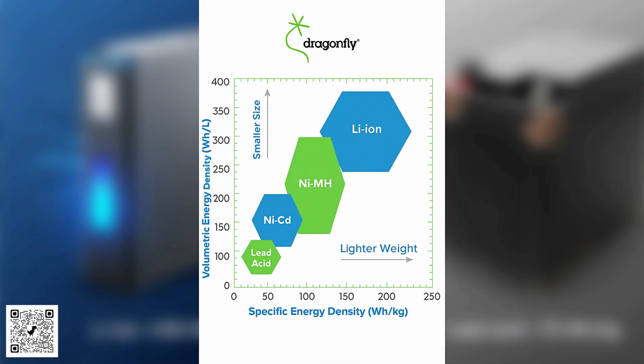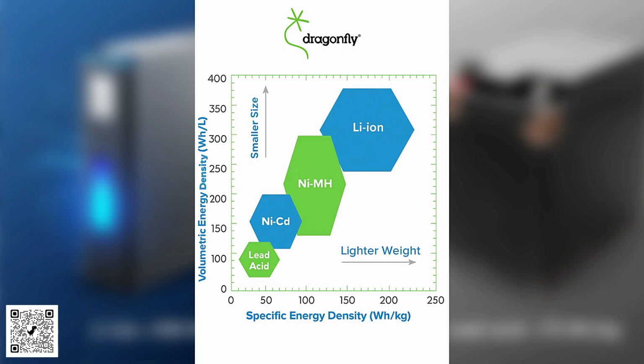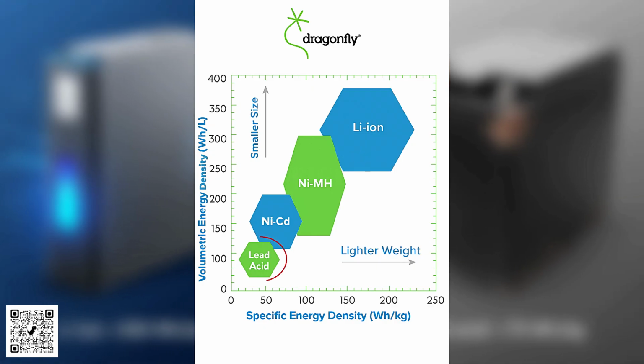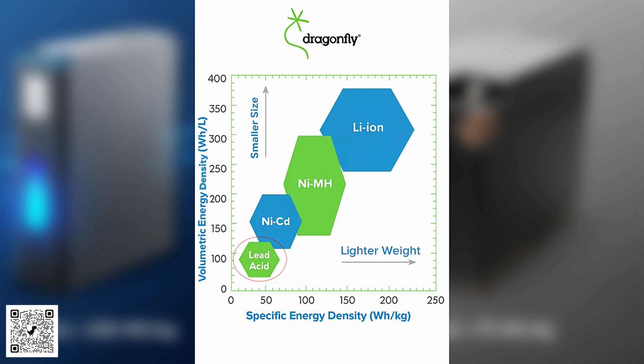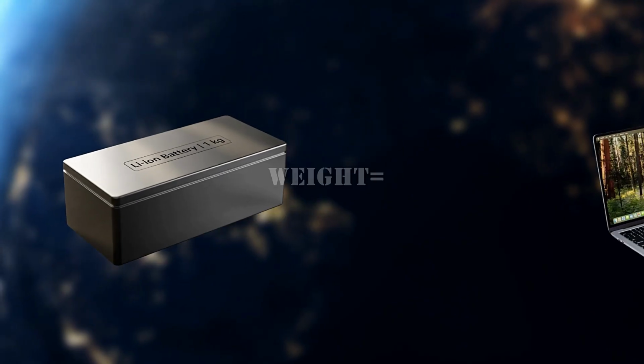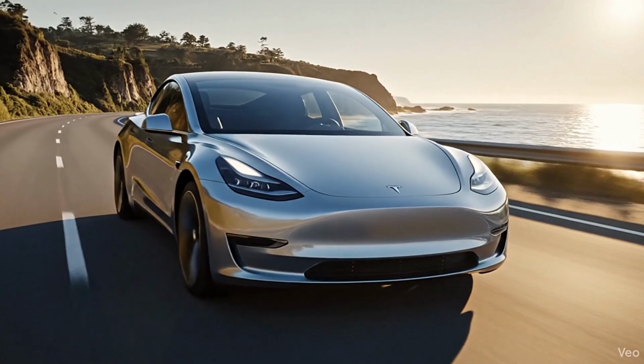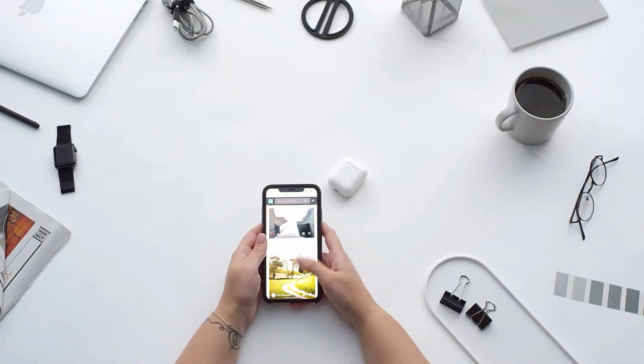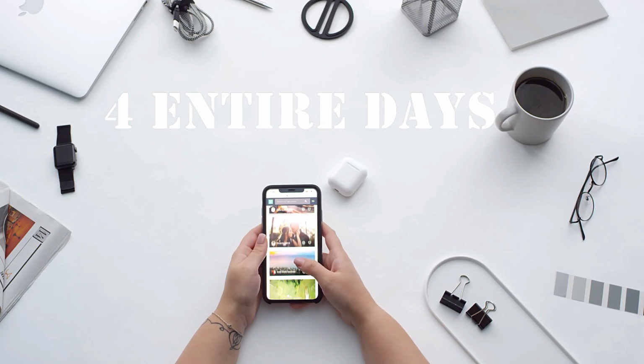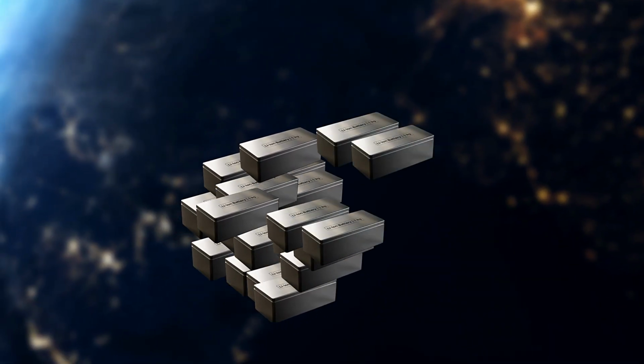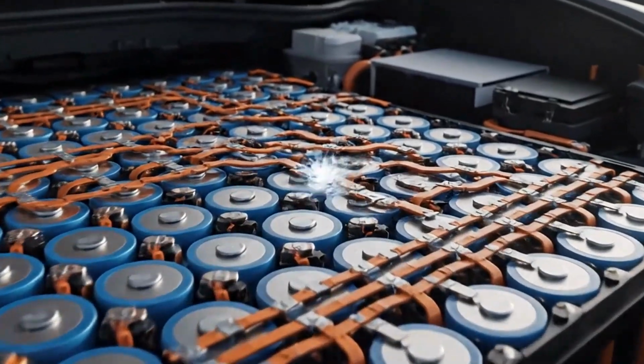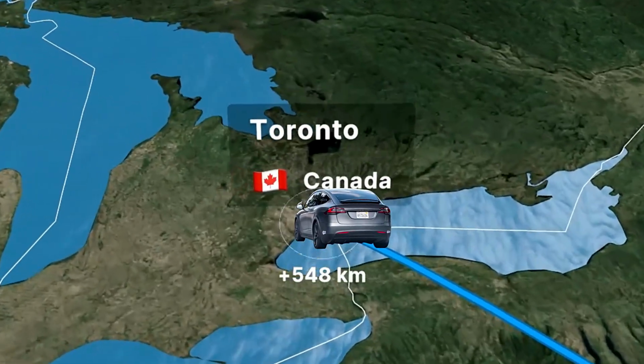And because lithium ions are so small, today's cells reach exceptionally high energy densities, up to about 330 watt-hours per kilogram, far above old lead acid, which is around 75 watt-hours per kilogram. Think of a single kilogram of lithium-ion battery as a small brick, about the weight of a laptop. That tiny brick can power an electric car for over 2 kilometers, or run your smartphone non-stop for 4 entire days. Stack just 300 of these bricks, and you've got a battery pack that can drive your EV from New York to Toronto without recharging.